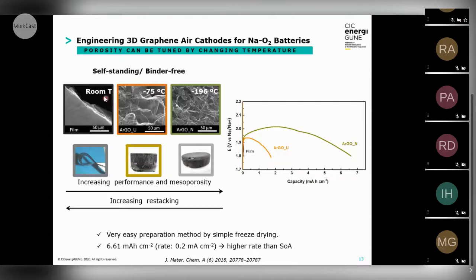First was to get it at room temperature. We can see that we can get a film. Then at minus 75 degrees Celsius, where you can get this kind of aerogel, and then at minus 196, where you can get more, like we say, more mesoporous-like material. We can see here that this increases the mesoporosity, and this decreases the restacking of the sheets in the case of the film.